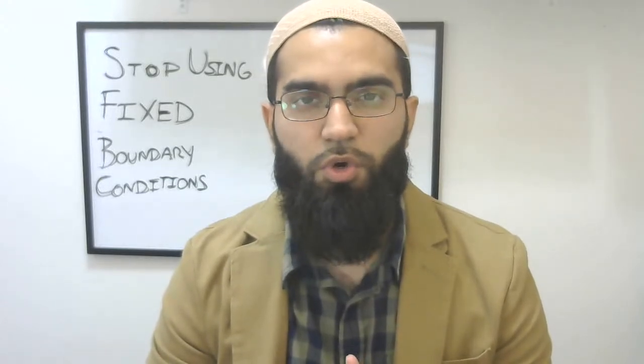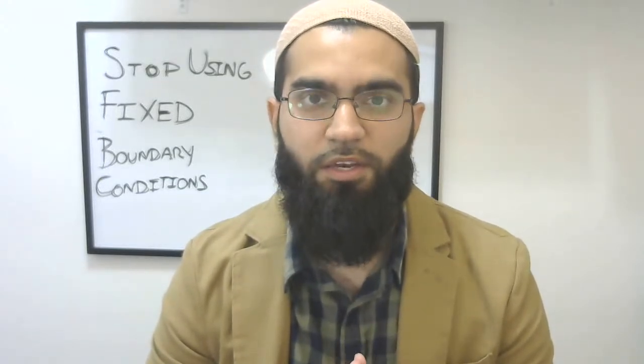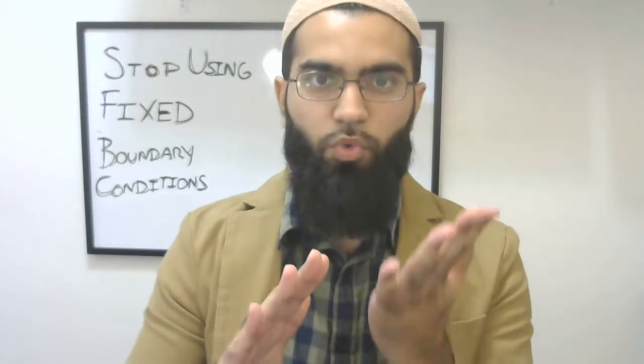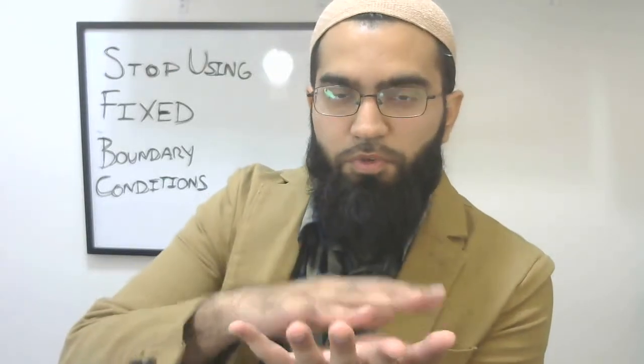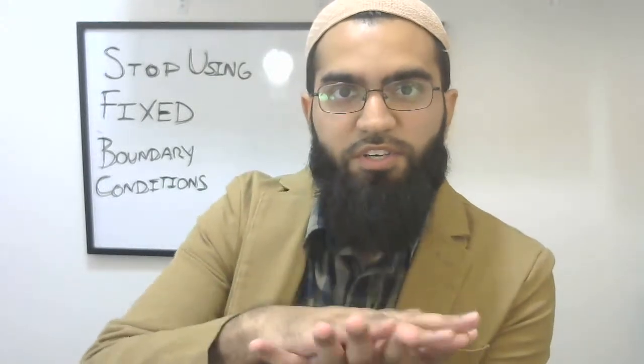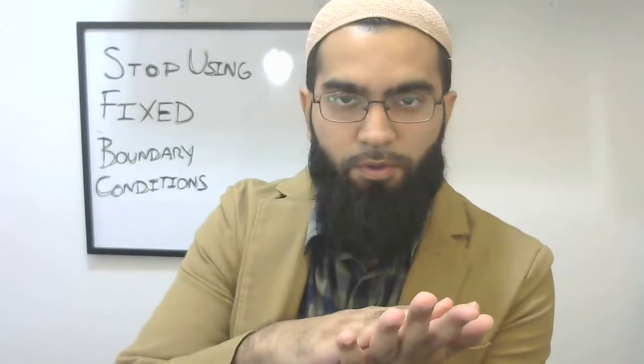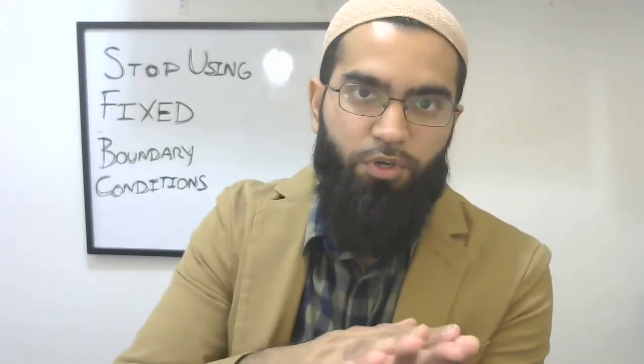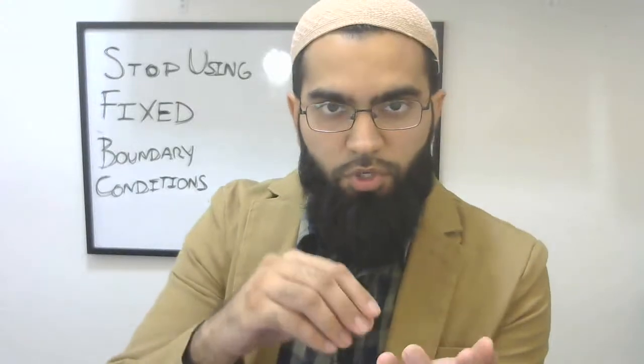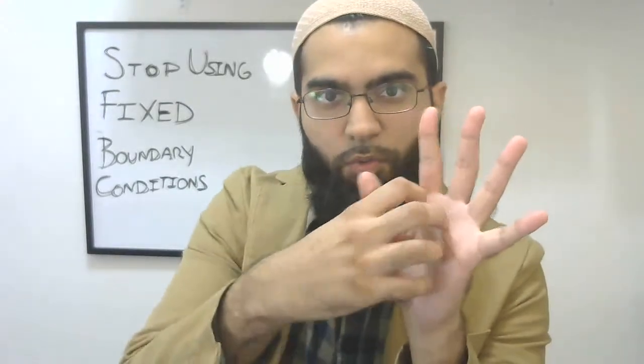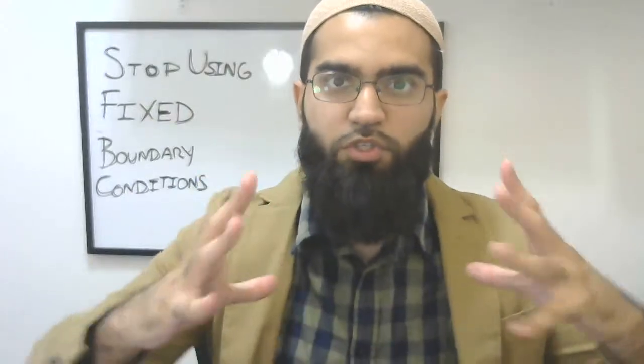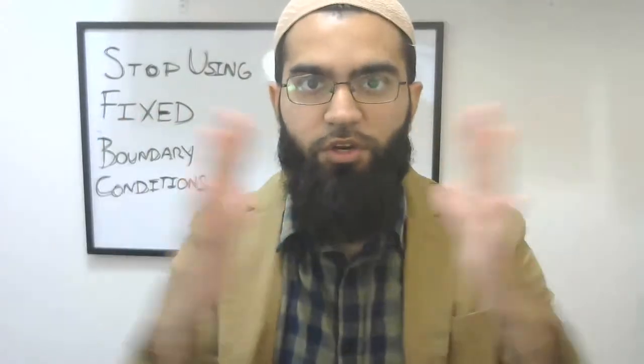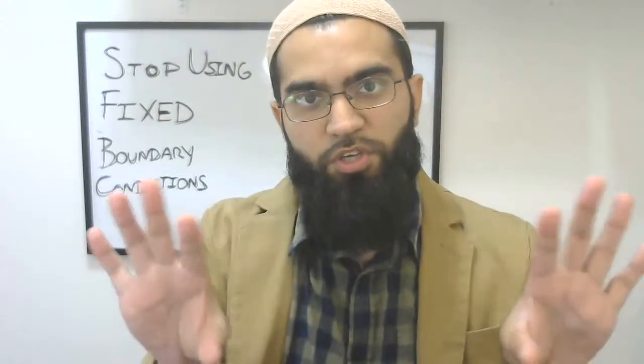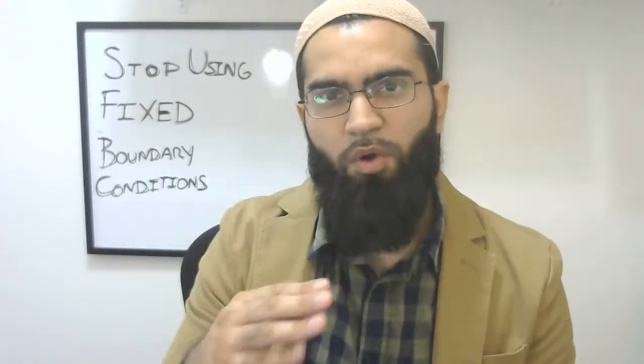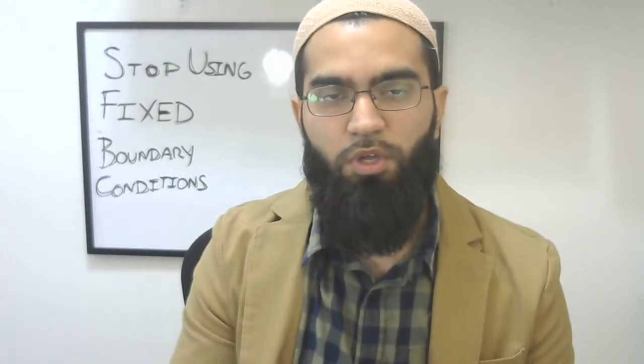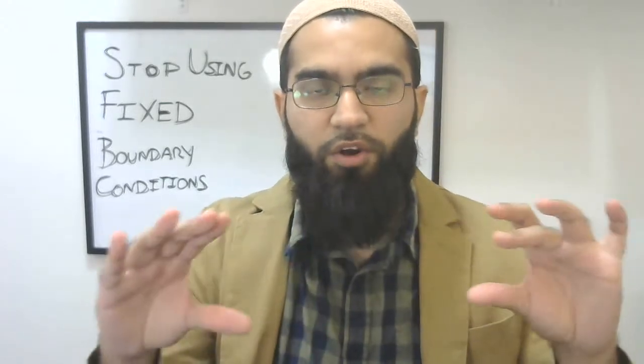Boundary conditions are extremely important to take into consideration. So when the disk was fixed, what does fixing mean? Fixing doesn't mean simply supported. Your static simulation won't work if you just simply support an object. So what happens if you fix the disk, when you apply a force to a material, it compresses in the direction that you apply the force, but it stretches out due to Poisson's ratio, to some amount of volume conservation that the material will attempt to achieve. So it'll actually get wider around the edges.